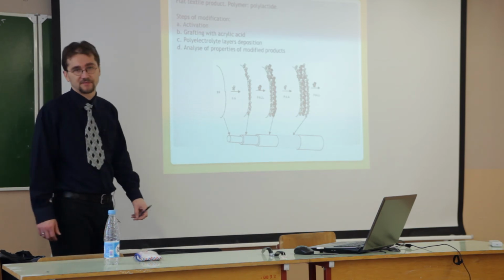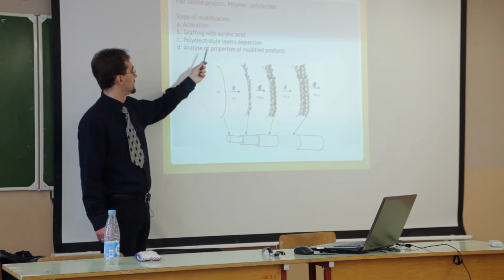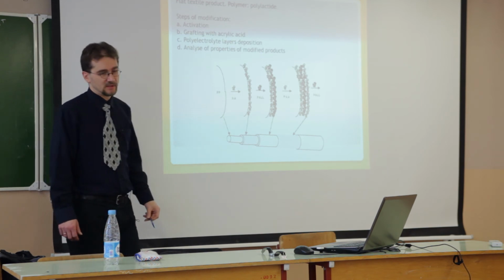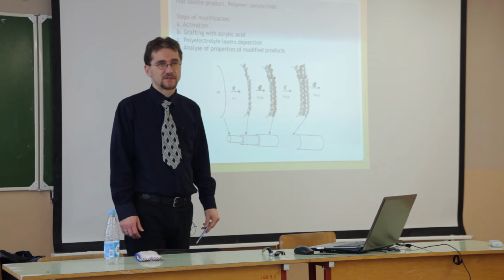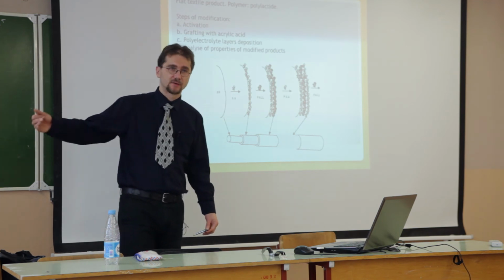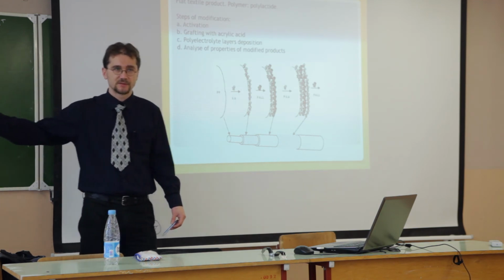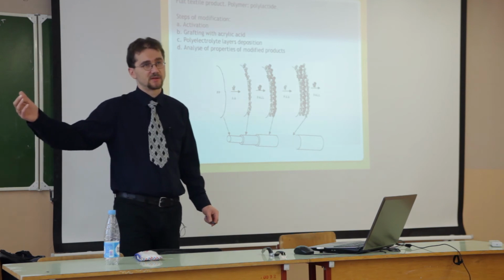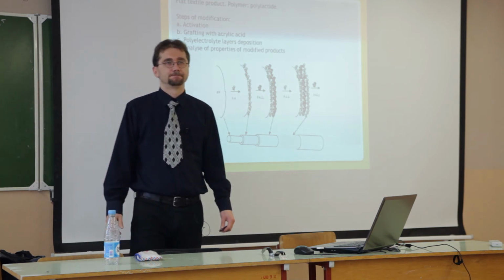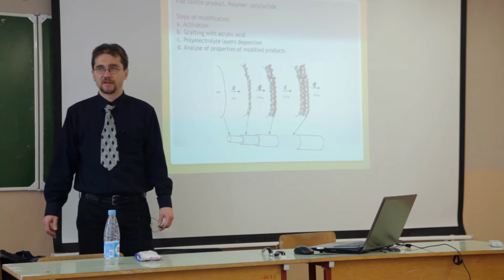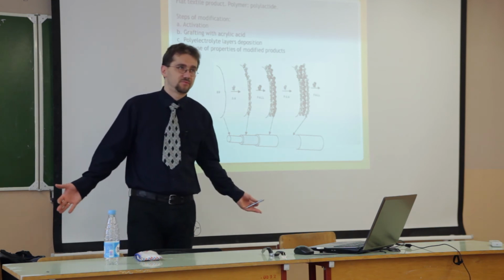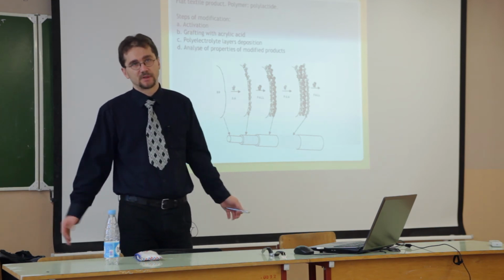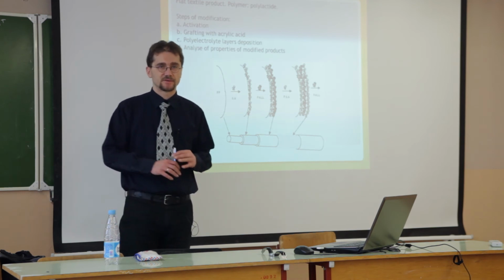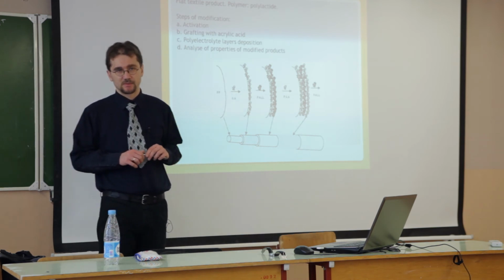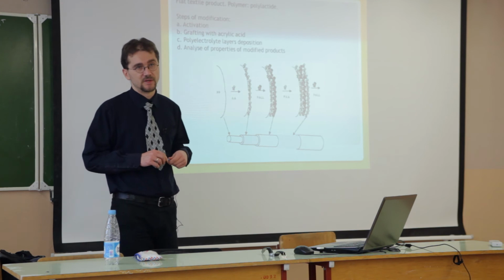And when we have grafted material, we can deposit polyelectrolytes, oppositely charged. So one on plus, second on minus, one on plus, next on minus, but not too much. In the literature, we can find applications of the layer by layer technique using, for example, 100 layers or something, but it is not possible for textiles. For textiles, we can deposit...